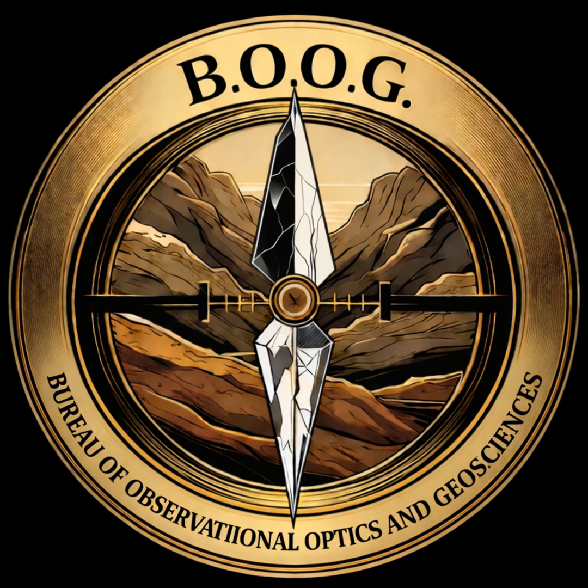But this process also left behind a massive population of newly nucleated, very tiny nanoparticles, the ones under 80 nanometers. The red filter ones. Exactly. Those tiny particles in the center give the core its deep red color. And as you move out toward the outer edges, the rim of the crystal. As you move toward the rim, the overall concentration of copper drops significantly, and the cooling timeline was slightly different. The copper particles there had enough heat to grow past the 80 nanometer mark, but the crystal cooled before they could grow into massive Schiller flakes. They got stuck at that intermediate 100 nanometer size.